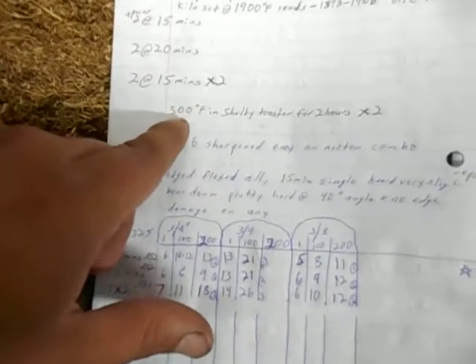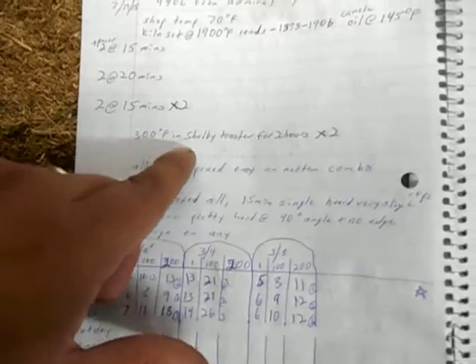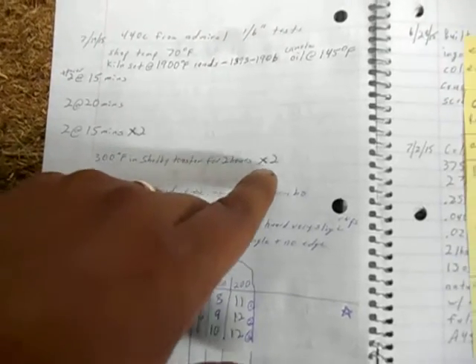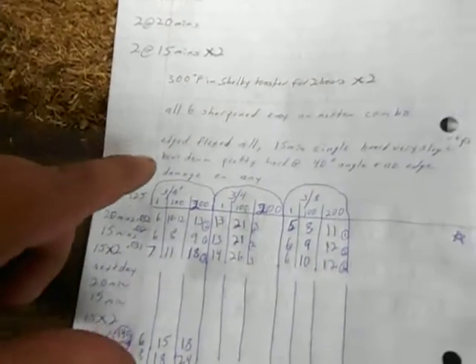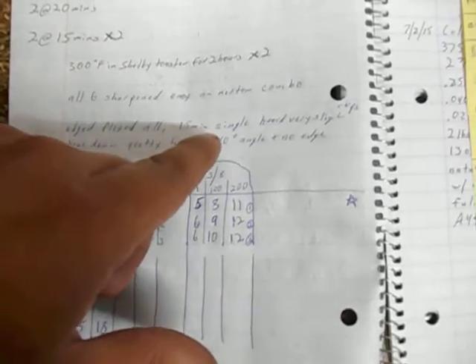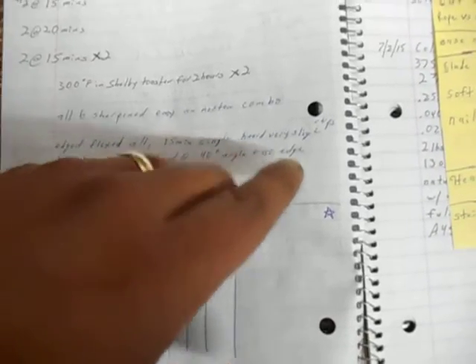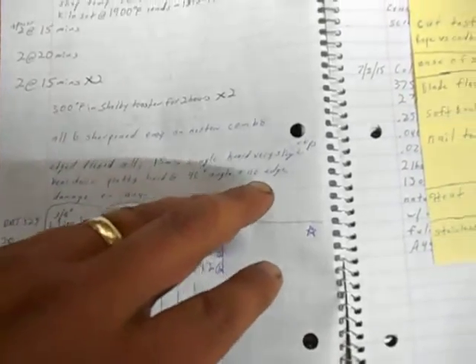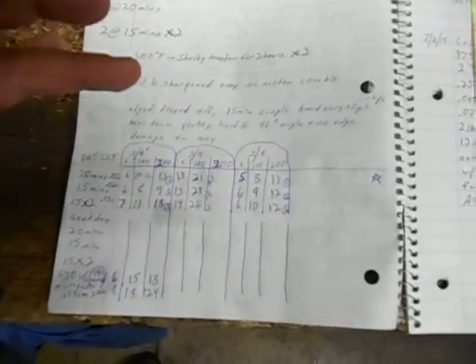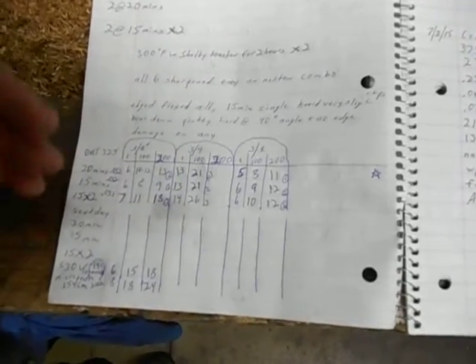Based on the testing prior, I did 300 degrees Fahrenheit for 2 hours. Let it cool to room temperature, and then did it again. All 6 of them sharpened up easily. We'll talk about that in a second also. Edge flexed them all. The 15 minutes single quench, I heard some very slight chipping in the edge when I did it, but I didn't see the chipping. Bore down pretty hard at about a 40-degree angle and no edge damage, and then did cutting tests.